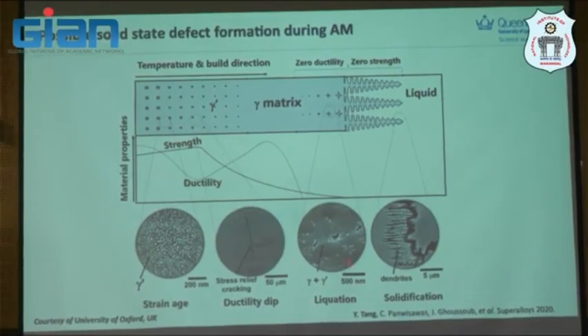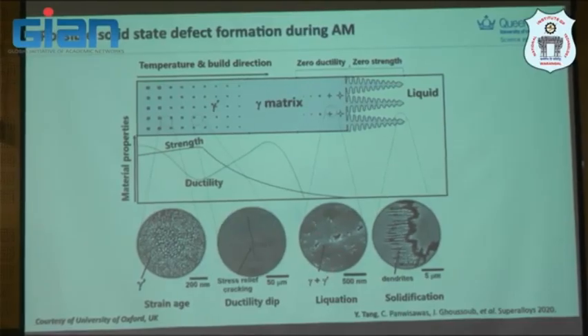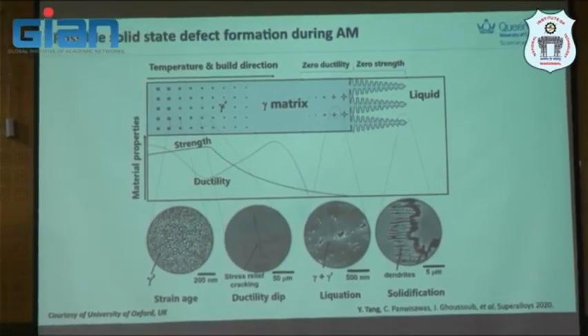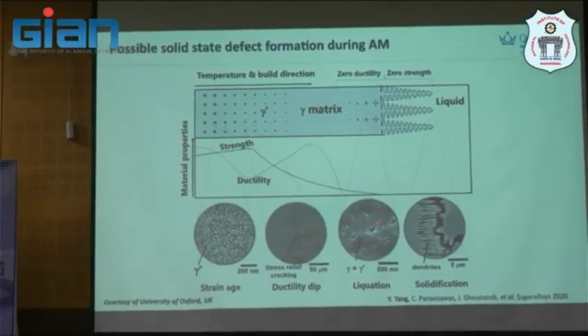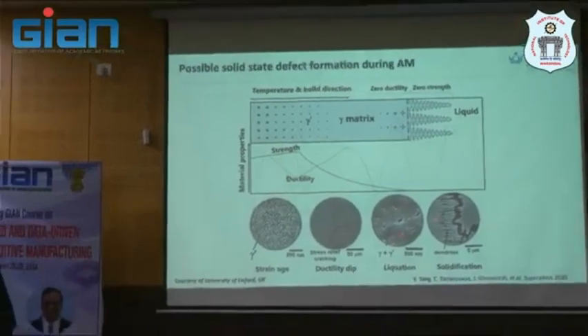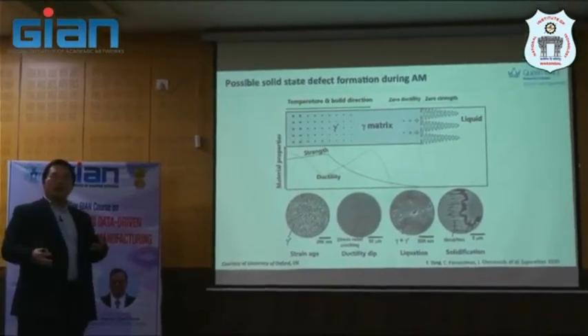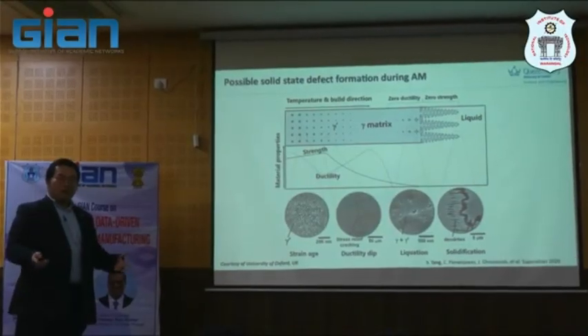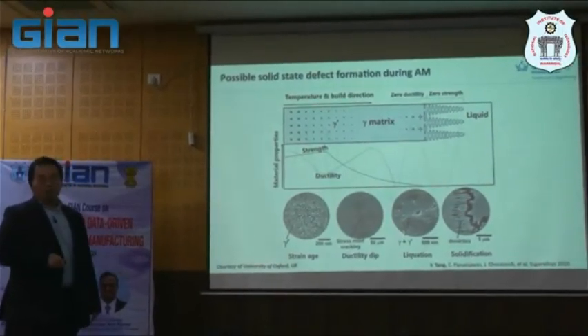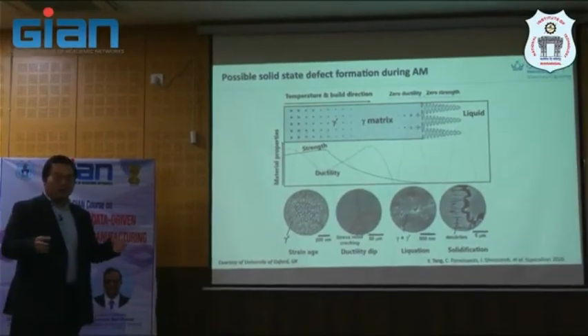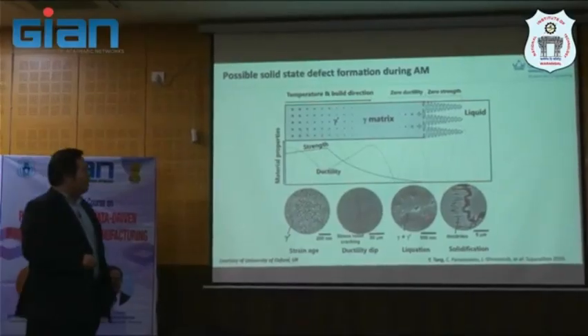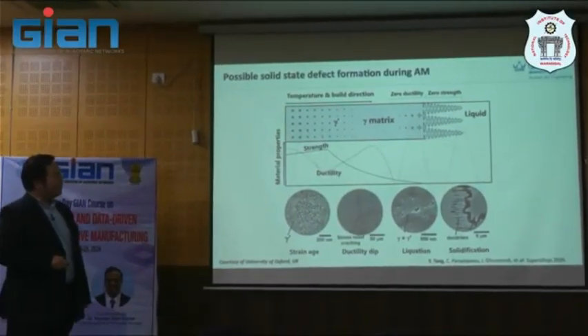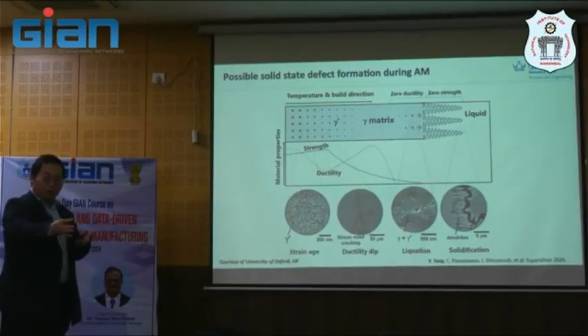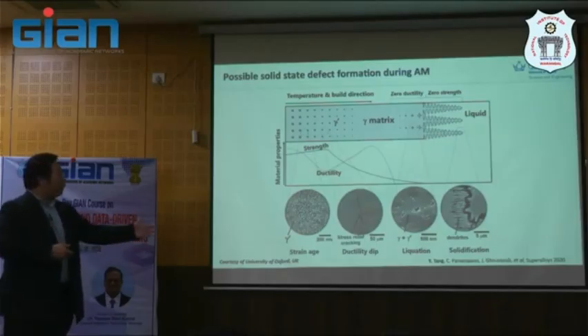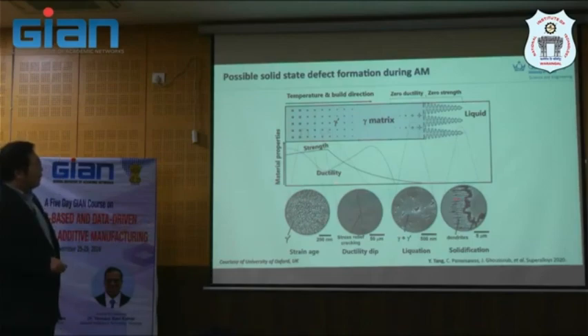You may also get some liquation during 3D printing: a liquid film which is formed during subsequent solidification. This is not new; it happens as well in casting, but in 3D printing it's commonly found a lot. But no one really knows this one. If you're not a metallurgist, you may not realize this is liquation cracking. It's related to incomplete solidification that leaves behind some liquid film inside, and that is a weak part for cracking. And another one is solidification cracking.